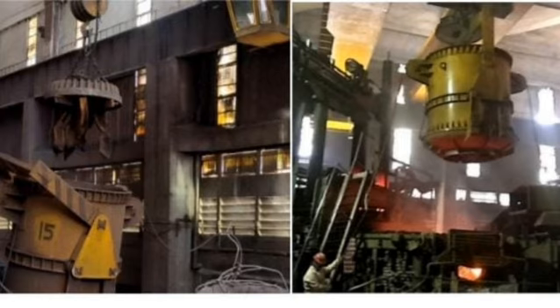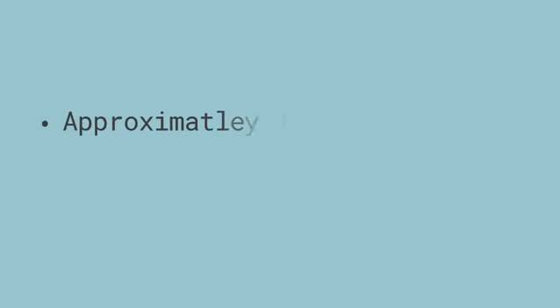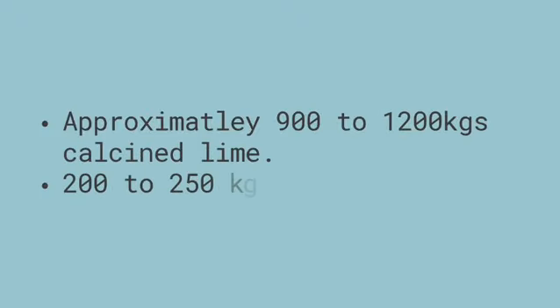Three. Bucket charging of scraps in the required order is done. The bucket opens from the bottom. The heavier metals are on the bottom, then followed by medium and light scrap like machine chips. Then charge approximately 900 to 1200 kgs calcined lime and 200 to 250 kgs coke/graphite.